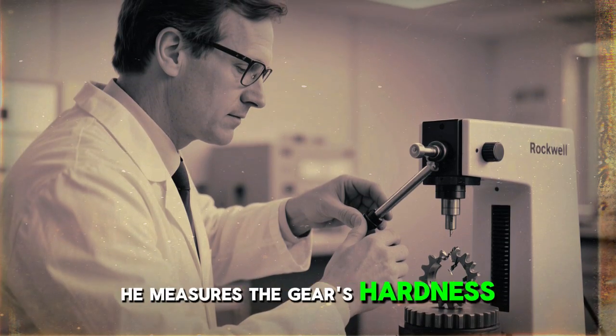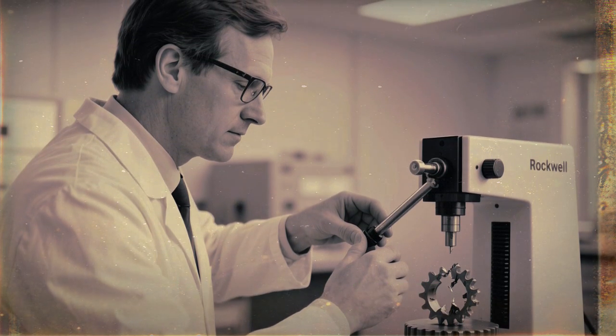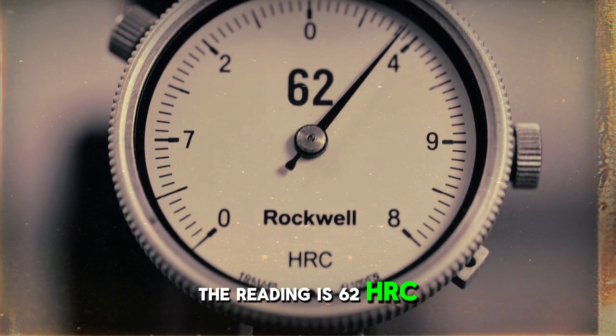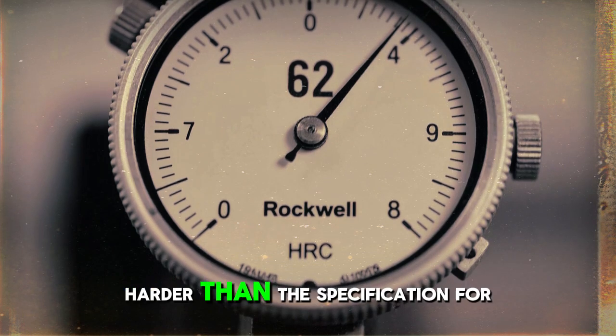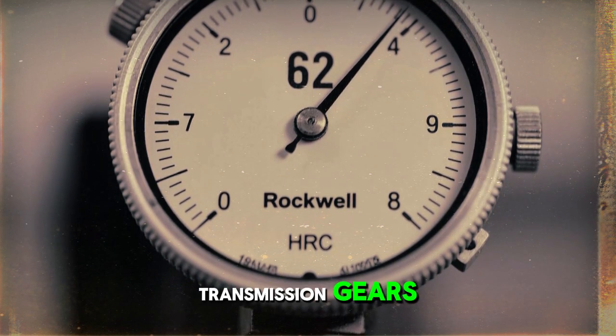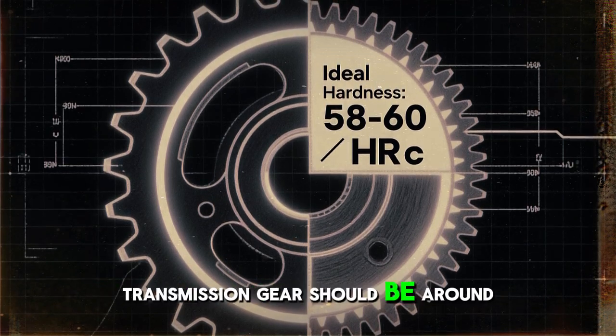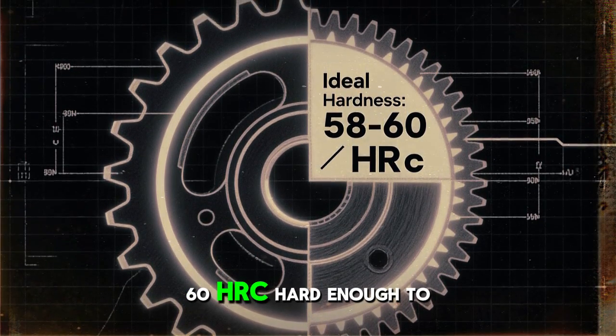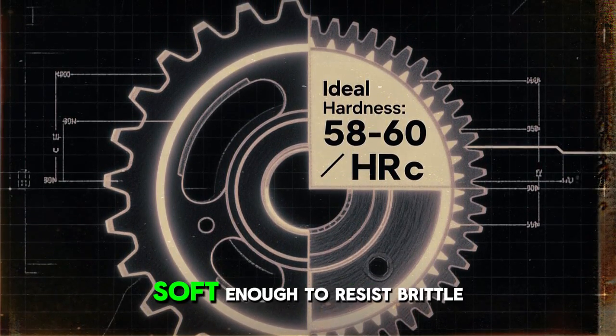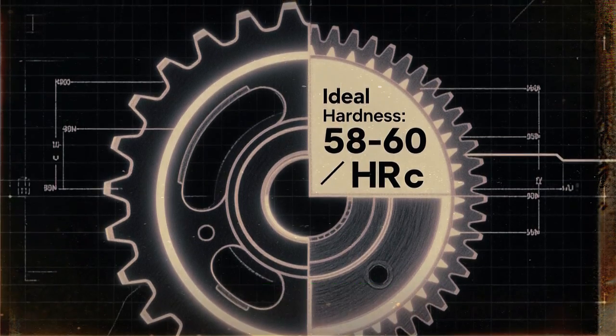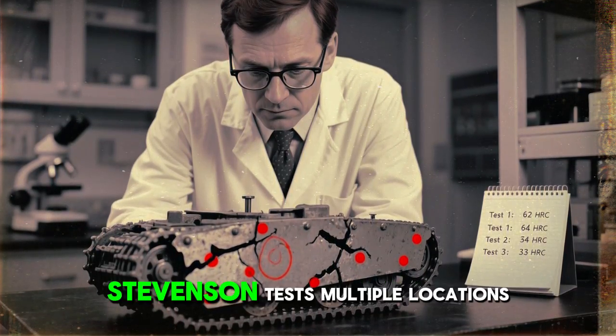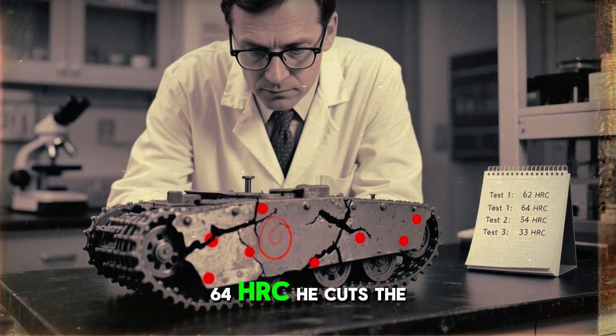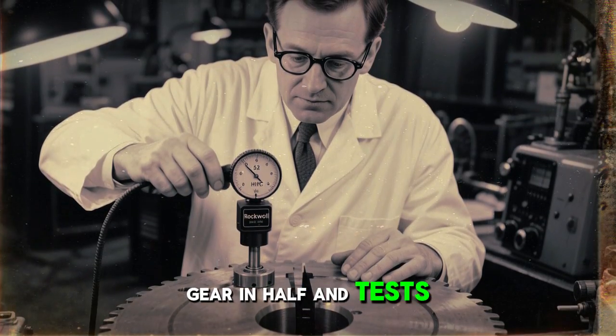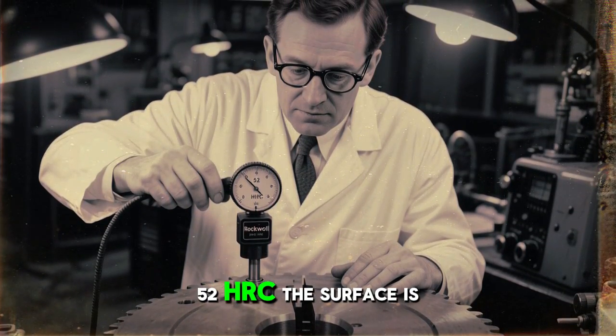He measures the gear's hardness using a Rockwell tester. The reading is 62 HRC, extremely hard, harder than the specification for transmission gears. Transmission gears should be around 58-60 HRC, hard enough to resist wear, soft enough to resist brittle fracture. This gear is too hard. Stevenson tests multiple locations. Surface hardness is consistently 62-64 HRC. He cuts the gear in half and tests the core, 52 HRC.